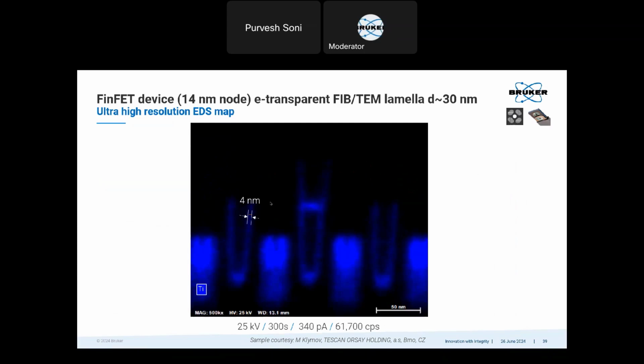And this is at even higher magnification, so you can see the feature that is there. So the tungsten layer that is here, physically, it's around 1 to 2 nanometer. And the EDS spatial resolution that I've got here is around 4 nanometer, which is quite good, considering that these measurements are done in SEM and not TEM.